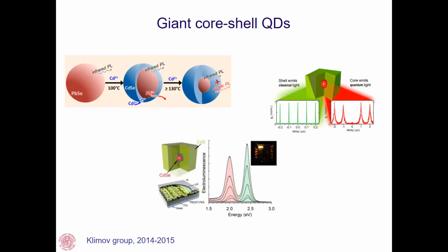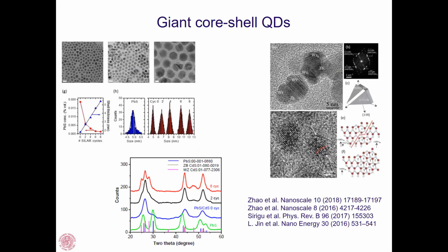But then, reasoning about the shell thickness, the Klimov group proposed a new strategy to broaden the optical properties of these materials, by proposing a very thick shell covering a very small quantum confined core. This kind of structure is called giant core shell quantum dots, and it's characterized by classical emission from the shell and quantum confined emission from the core. Tuning the optical properties of these crystals is extremely fascinating.